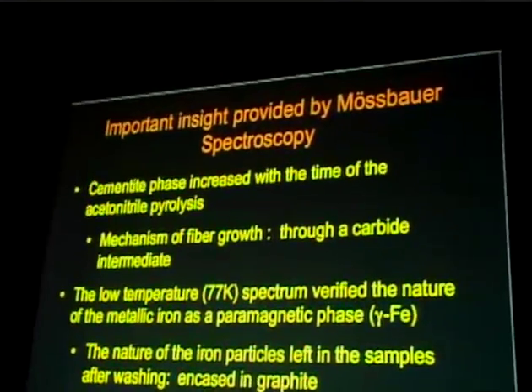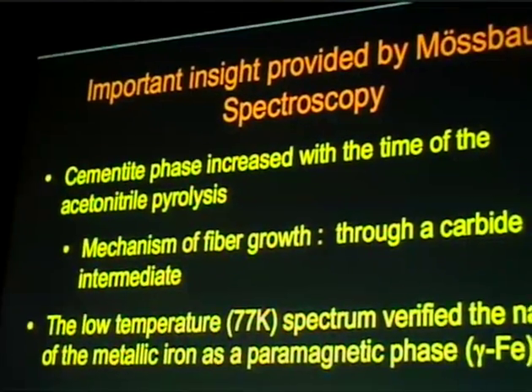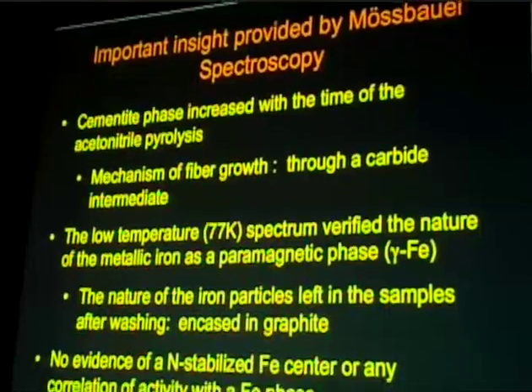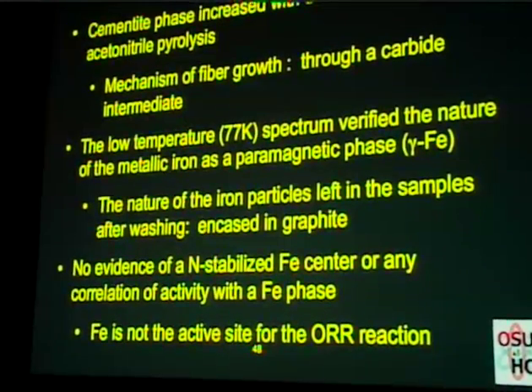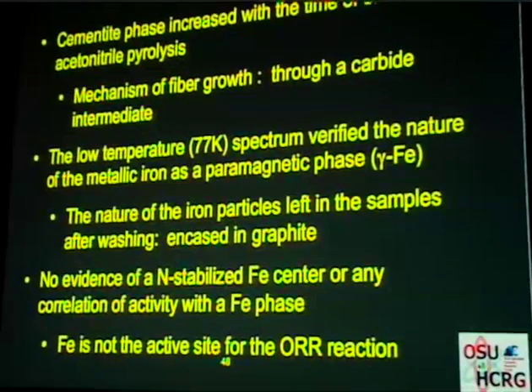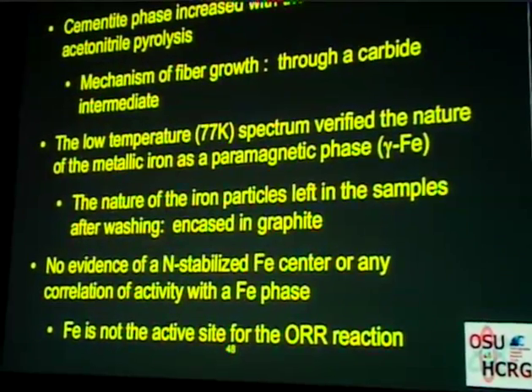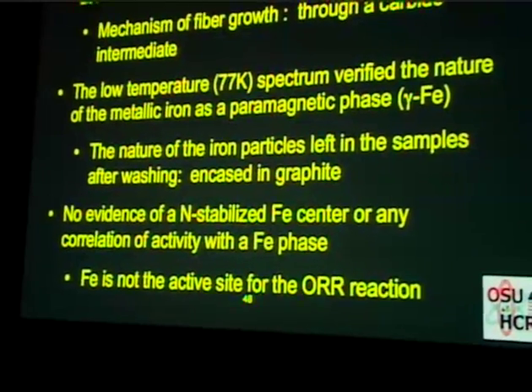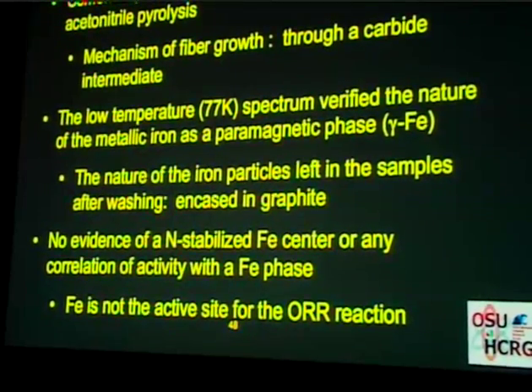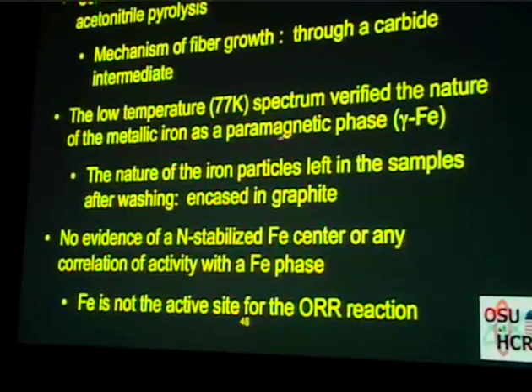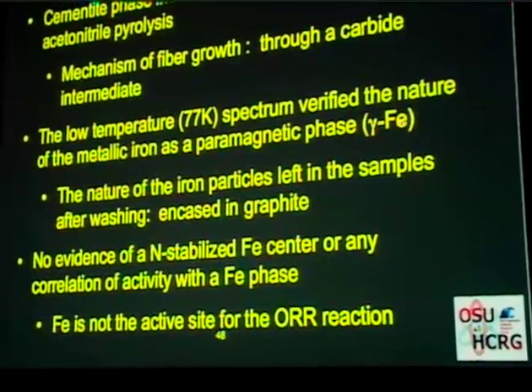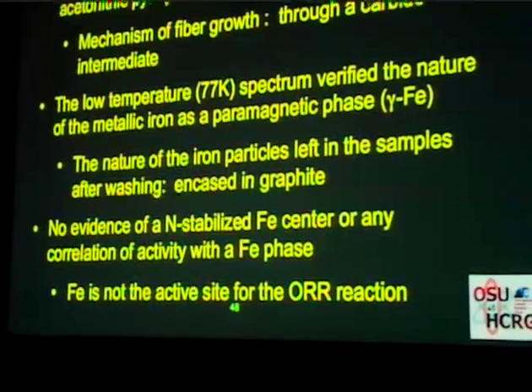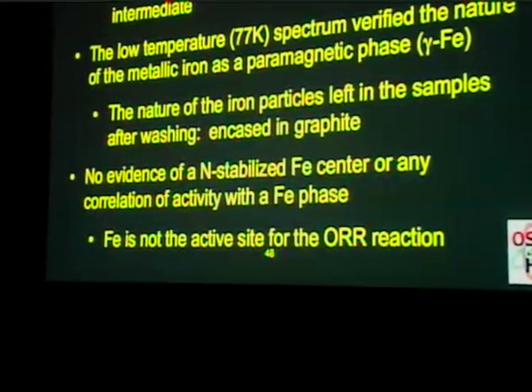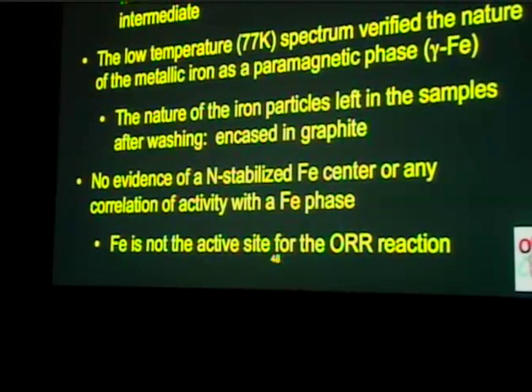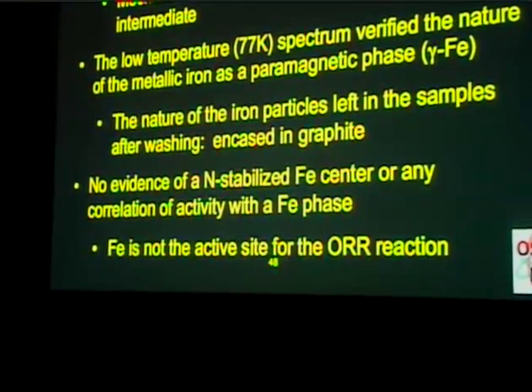Mössbauer spectroscopy was really important because it provided some insight. First of all, it showed that the cementite phase is increasing with the time of acetonitrile pyrolysis, and this really gave us insight about the mechanism of fiber growth through a carbide intermediate. We have done low temperature 77K Mössbauer spectroscopy to verify the nature of the metallic iron as paramagnetic phase, gamma iron, and the nature of the iron particles left in these samples after washing gave us the indication that they could only exist if they are completely encased in graphite.